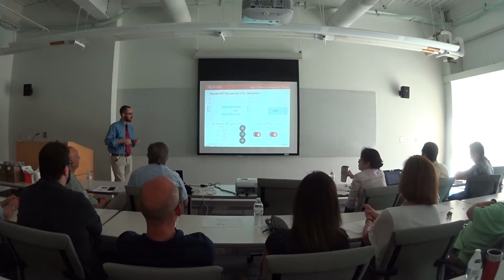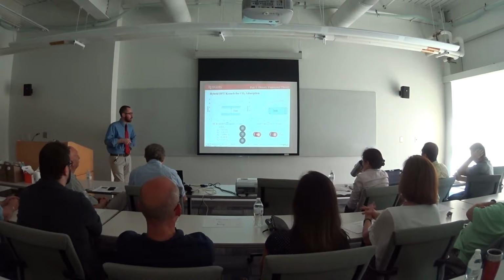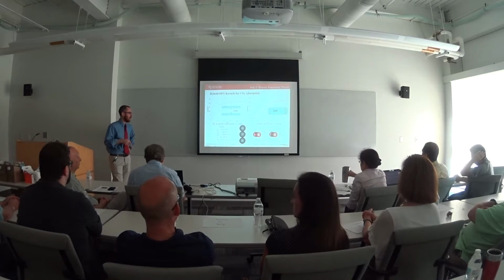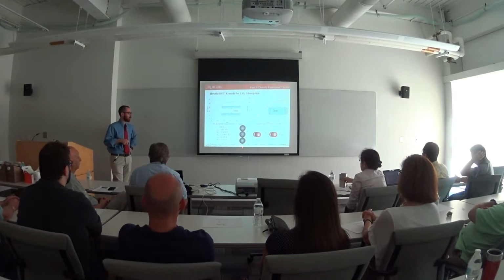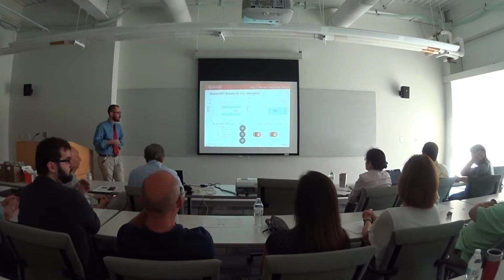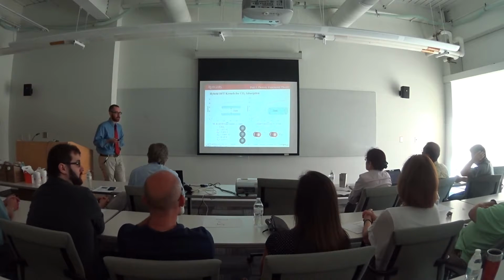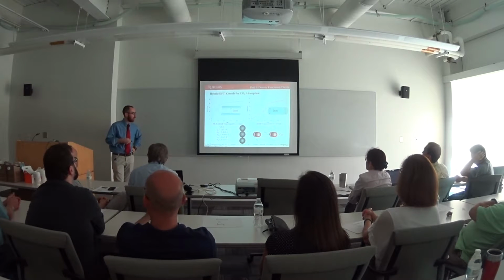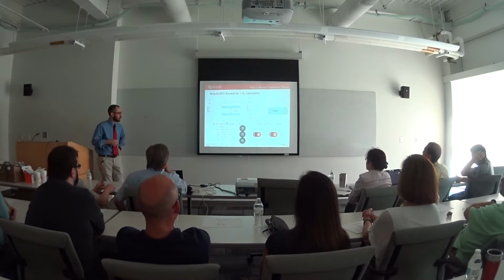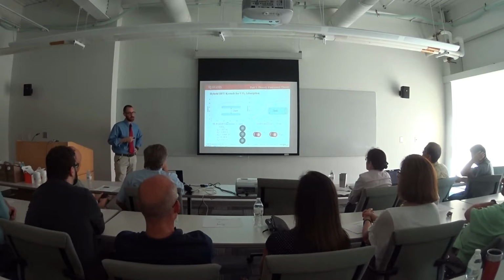We used a Lennard-Jones parameterization to take care of both the solid-fluid and the fluid-fluid interactions in CO2 and carbon, and also argon and carbon. And one thing that's important to note is, of course, that CO2 is not a Lennard-Jones sphere by any stretch of the imagination. However, we can approximate the CO2 molecule by a Lennard-Jones sphere if we correctly parameterize our model.